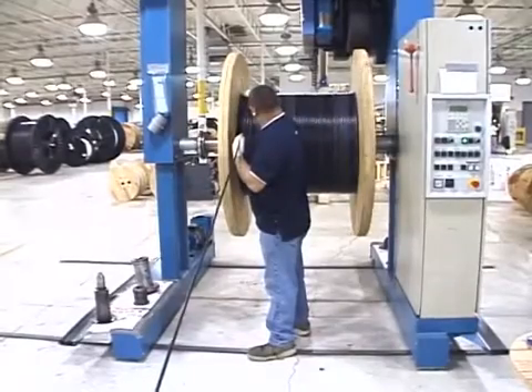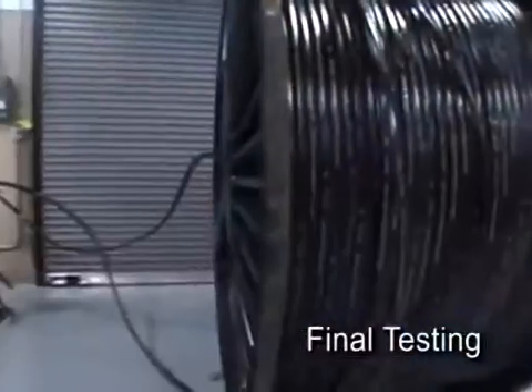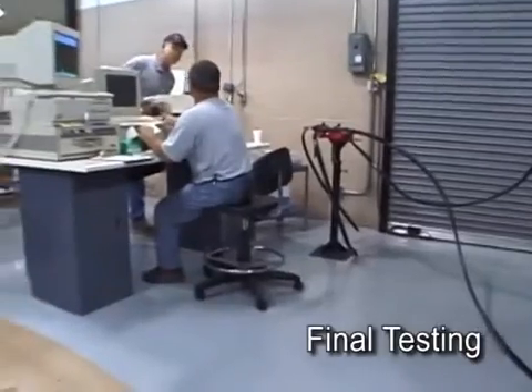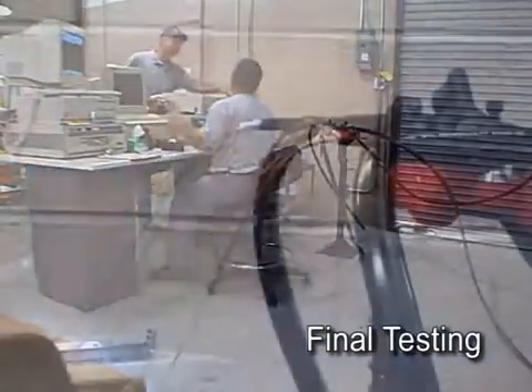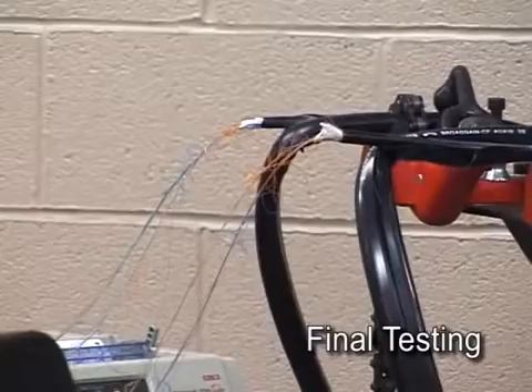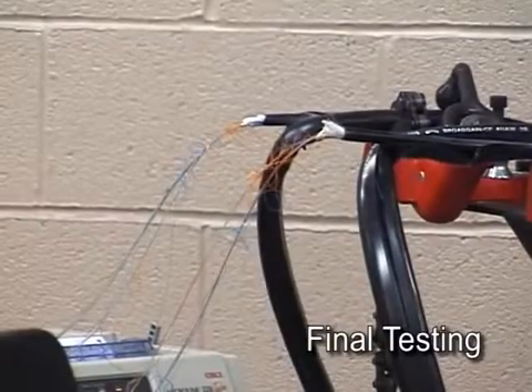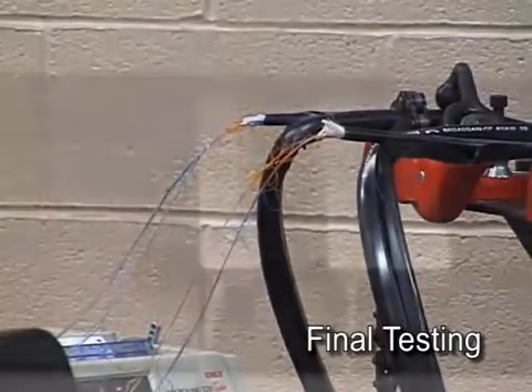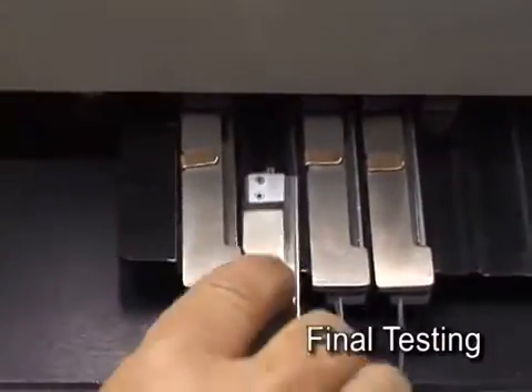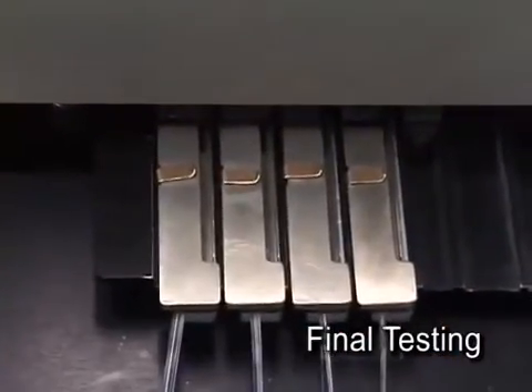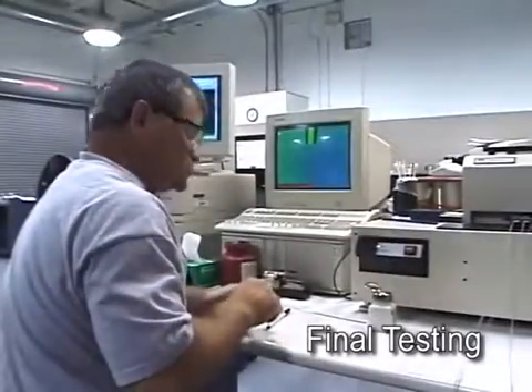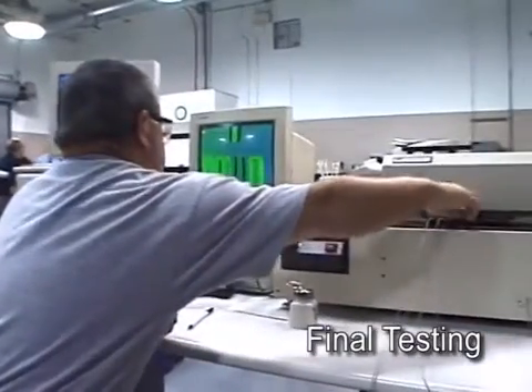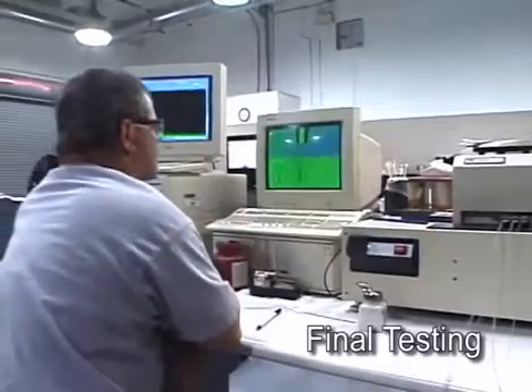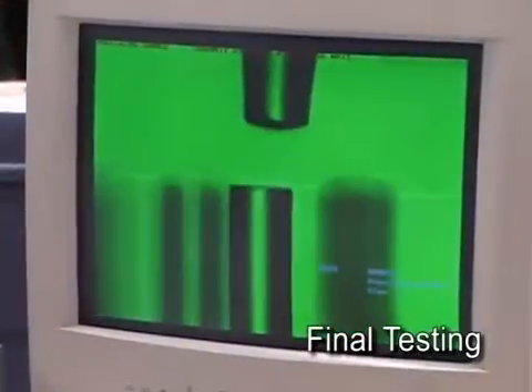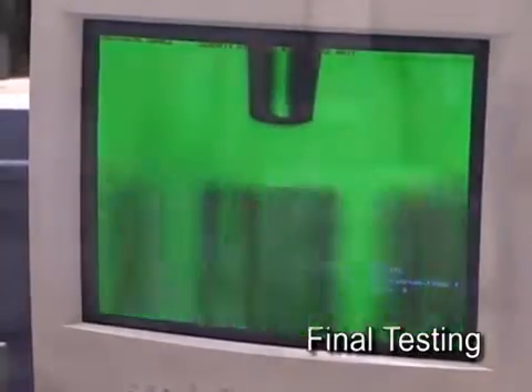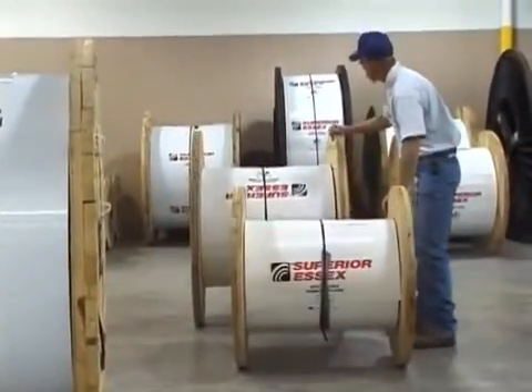The cable must go through our final test process to ensure that all fibers meet optical specifications established by Superior Essex. A short length of cable is prepared to expose the fibers to be tested. In this example, the technician is testing a ribbon fiber cable. All of the ribbons within the cable are prepared and inserted in test fixtures that are sequentially plugged into an automated test station. In this way, each fiber and every ribbon of the cable is quickly tested and compared against our specifications. Once the cable passes all tests, the cable ends are sealed and the reel is ready for shipment.